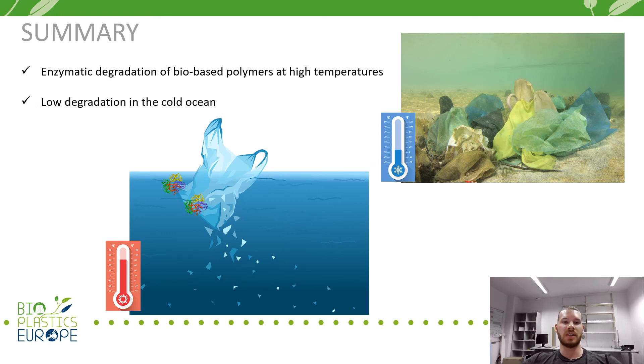We have seen that different biobased polymers are hydrolyzed by different enzymes. The biobased polymers have a higher enzymatic degradability than petroleum-based polymethylmethacrylate. Highest degradation rates were observed at temperatures of 30 degrees Celsius and beyond. Accordingly, the degradation of the biobased plastics is mostly very low in the ocean. pH-stat titration is a useful method to evaluate the enzymatic degradability of natural and synthetic polymers under controlled laboratory conditions.